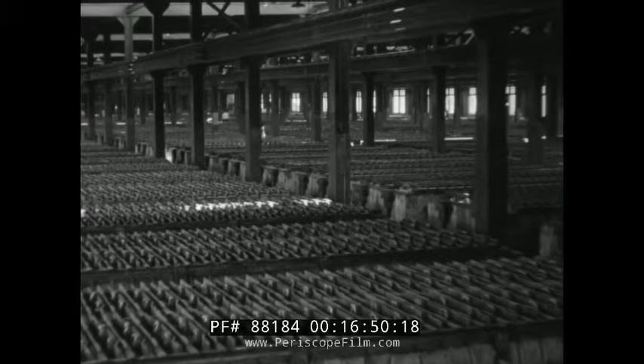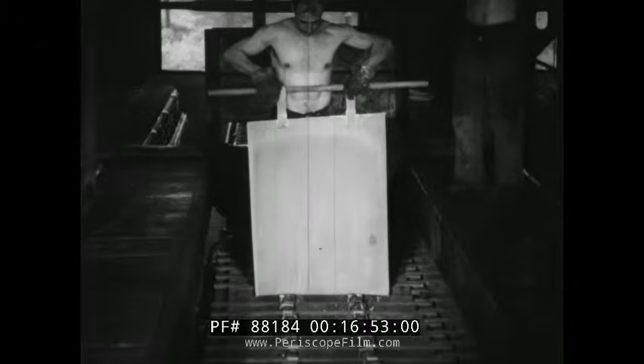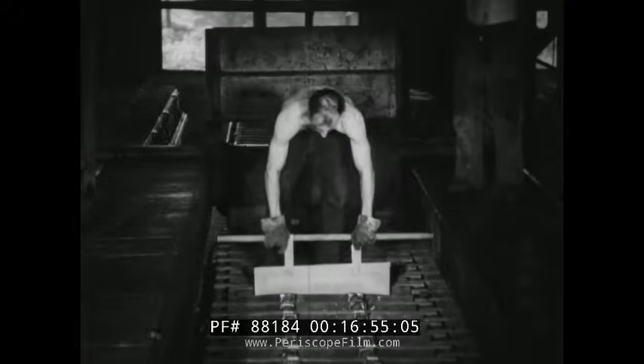The electrolytic tank houses cover approximately 15 acres of space. Here, the crude nickel anodes are slowly dissolved and redeposited as pure nickel cathodes. After 14 days, they are removed from the tanks.